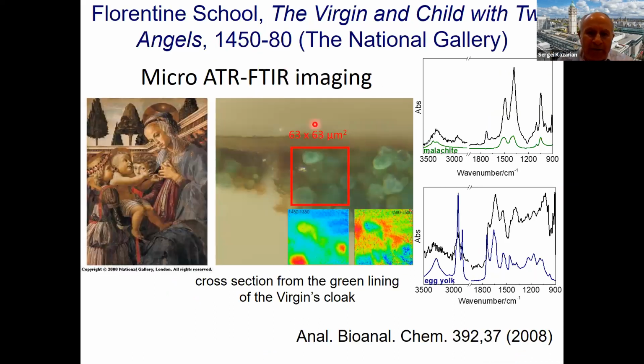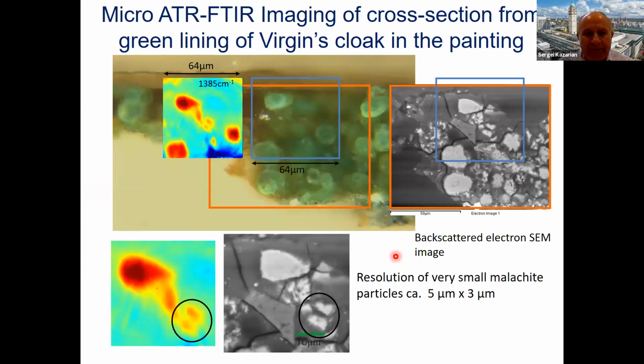Another example was a painting from the Florentine school, where we were able to detect here particles of malachite. Malachite, if you compare with a reference material, you can see some bands overlap. But between or here, you can see, we were able to detect again an egg product containing proteins via amide bands. Of course, here the amide bands may not be entirely clear because they overlap with one of the antisymmetric vibrations of carbonate of malachite, but the assignment was unambiguous, so we were able to see binding media as well. And this might be a slightly better view. You can see, for example, these very small particles, maybe a few micrometer. They were confirmed, of course, by scanning electron microscopy. But organic materials have been detected by these infrared studies.